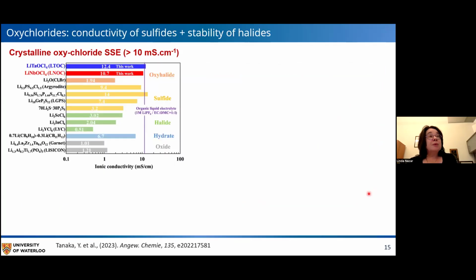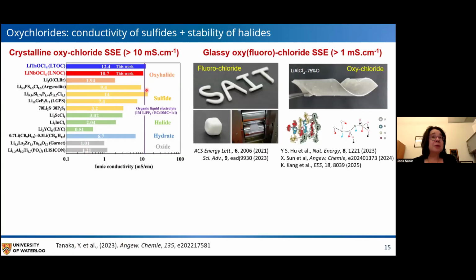So then I will switch gears again now to the oxychlorides. And these have the conductivity of sulfides and the stability of the halides. This diagram comes from this paper by Tanaka, published in Angewandte Chemie, also Panasonic. And this shows the conductivity of the lithium tantalum oxychloride and lithium niobium oxychloride, which they reported on, compared to some other materials such as argyrodite, LGPS, and some of these halides. And so you can see that really the conductivity is very high, similar to that of the sulfide. But as I said, the stability is basically the same as the halide.